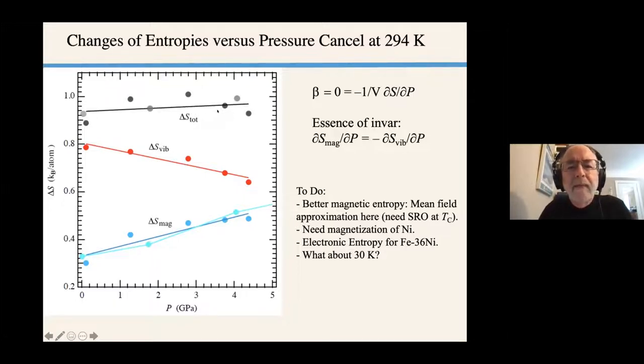The total is kind of flat. We still have to take into account the electronic entropy a little better and do a better job on the magnetic entropy. We also need to take into account the magnetization of nickel too, which I think will cause this curve to decrease since it doesn't change so much with the Invar transition and the spin is smaller anyway. So I think we have a basic explanation of Invar. The change in the magnetic entropy with pressure is counteracting the change in vibrational entropy with pressure. And therefore, the thermal expansion has to be zero for this material.